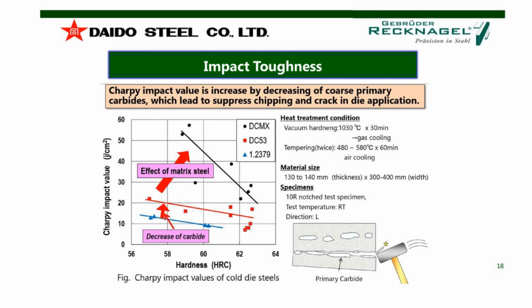Yeah, what about the impact toughness? It's very important to understand that the most negative impact on the toughness comes from the coarse carbides, the primary carbides. And as the picture in the bottom with the hammer shows, the biggest killer of the toughness are the primary carbides. That's the point you have to understand.